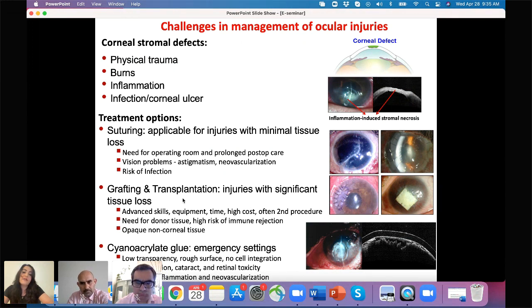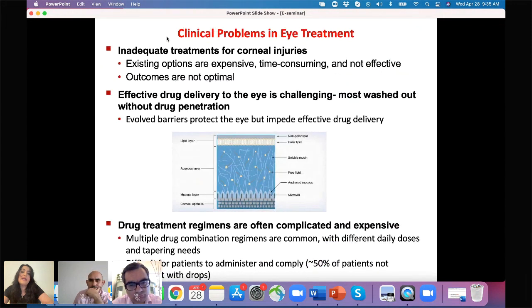However, all these techniques suffer from several limitations, and one limitation is vision problems. There is a risk of infection for grafting and transplantation, a need for donor tissue, and also a high risk of immune rejection. In the case of cyanoacrylate, the limitations are low transparency and a very rough surface. There is no cell integration inside cyanoacrylate, and also there is a risk of infection and significant inflammation. So there is a big problem in treatment. We have inadequate treatments for cornea injuries. That is one clinical problem in eye treatment.